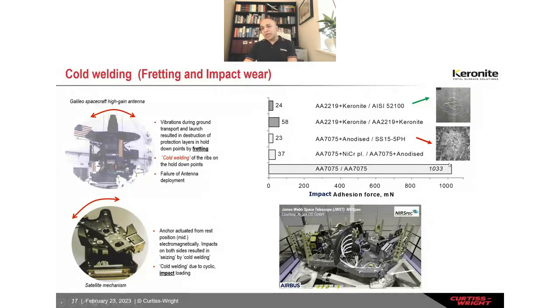This picture here is showing again the two, between the hard anodized and on the right. This is the top one here. You can see my mouse here is the Keronite PEO. After impact testing, there's no destruction of the surface. All this you can see is a steel ball transfer, steel material transfer to the Keronite surface. On the bottom one here, the hard anodized coating is completely damaged.